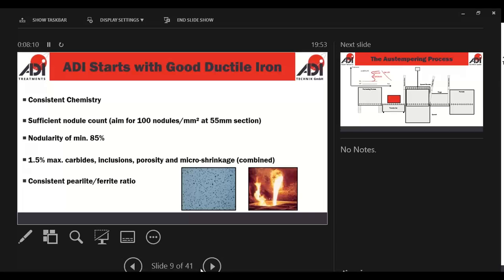And when I say that, there's a list of good things we need. We start off with a consistent chemistry. Because we're involving a quenching process, we require hardenability. Hardenability is not the same as hardness. If you want something of a high hardness, you add alloying elements like copper, maybe nickel, to get a pearlitic structure. Hardenability is adding these alloys so that when we quench them, we don't form pearlite. We avoid the formation of pearlite, and we form this austempered matrix, ausferrite.